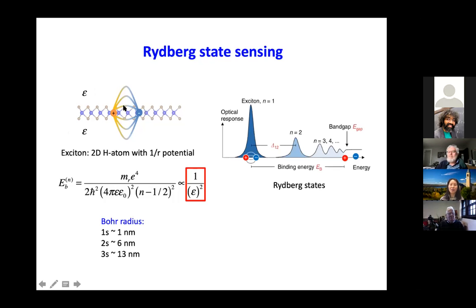So imagine that you have a single sheet of semiconductor. Then the Coulomb interaction, in this case, between an electron and a hole generated by optical excitation, will be very strong, because you can naively think about all the electric field lines responsible for the Coulomb interaction between those 2 particles. They are very much outside your material, so they are not screened too much by anything. So screening is poor for a single sheet of material. Therefore, the electron-hole interaction is strong, so the binding energy can be as large as half an eV.